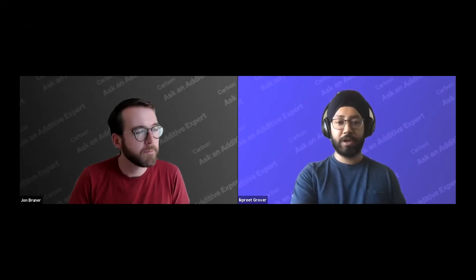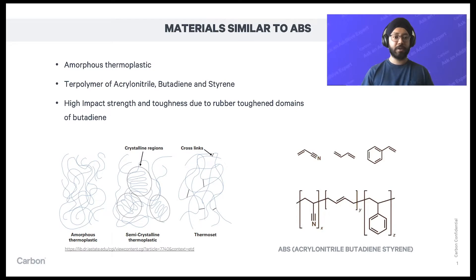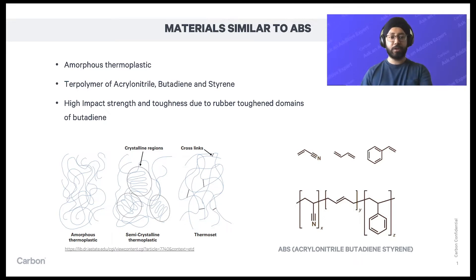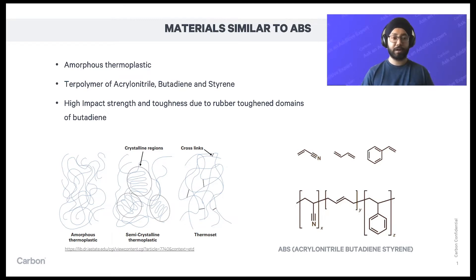So you have these three components, and of course there are a lot of other additives — and a lot of varieties of ABS with different characteristics. You prepare ABS using these three constituents and can adjust the proportion of each to control the end set of properties. If you increase styrene, it's going to be more rigid with a better, shinier surface finish. If you have more butadiene, it's going to be tougher and can take in a lot more impact strength.